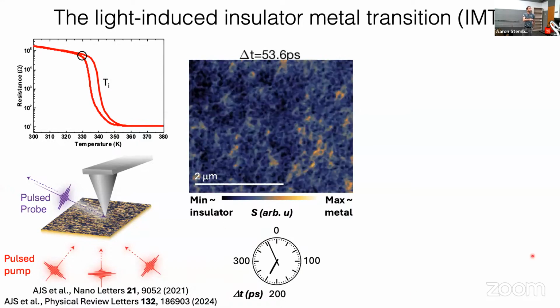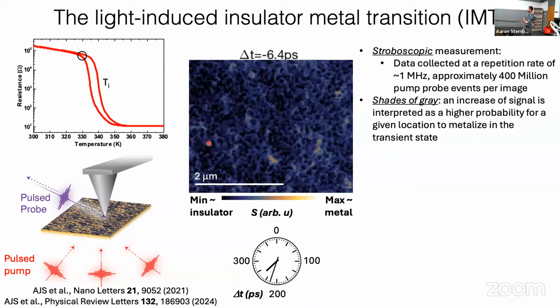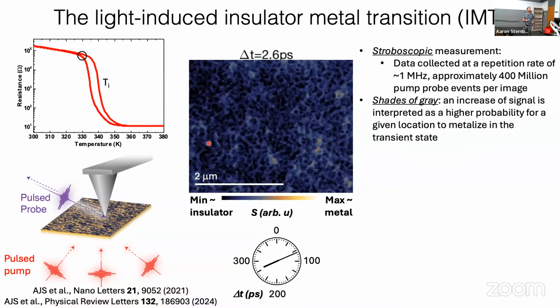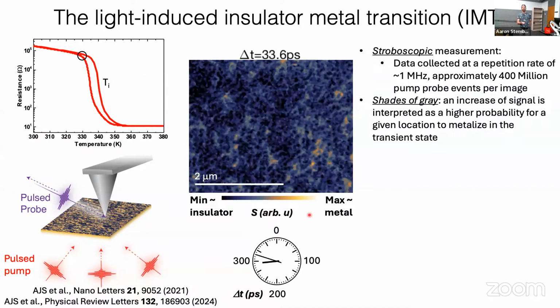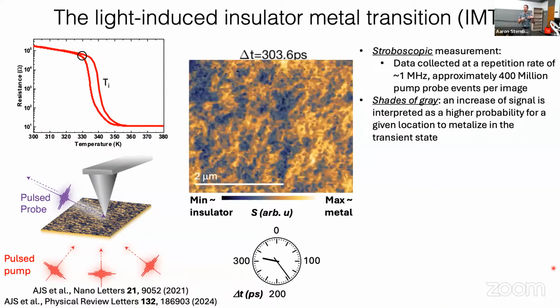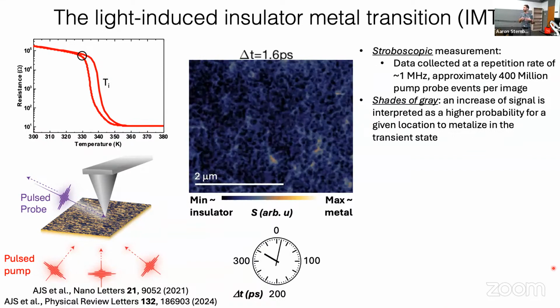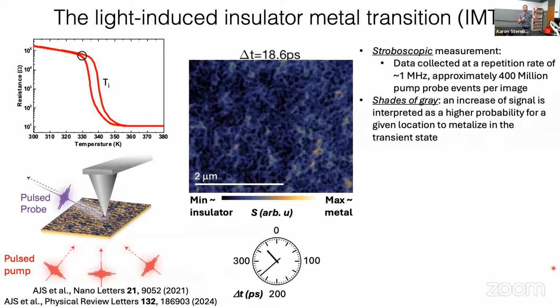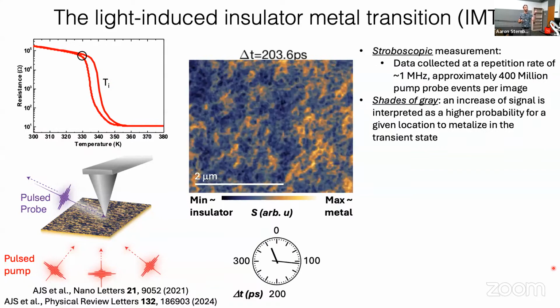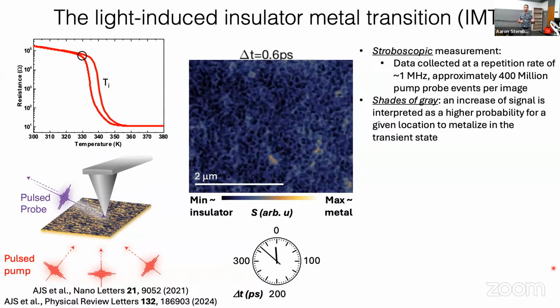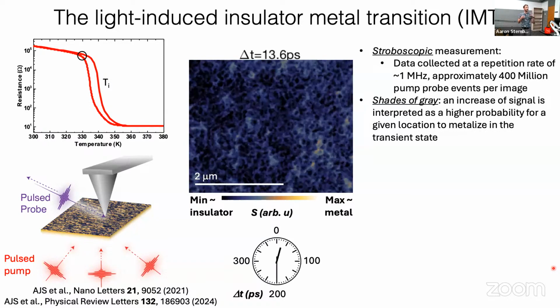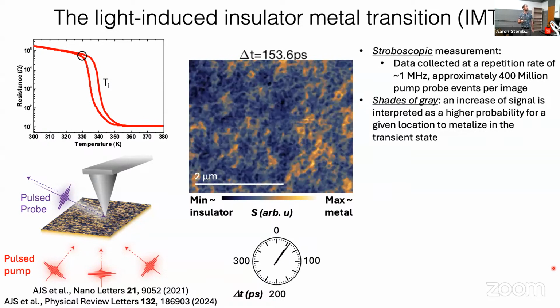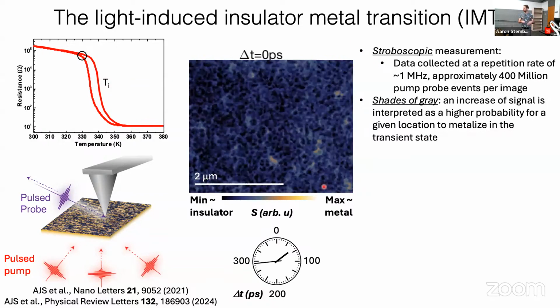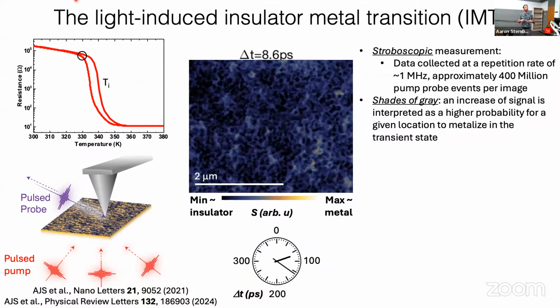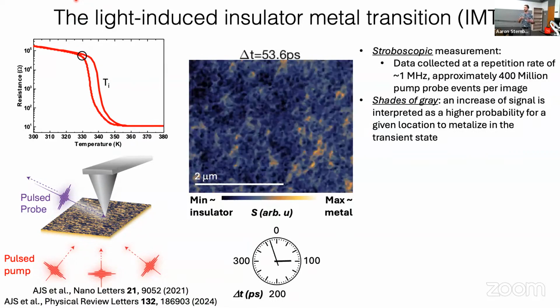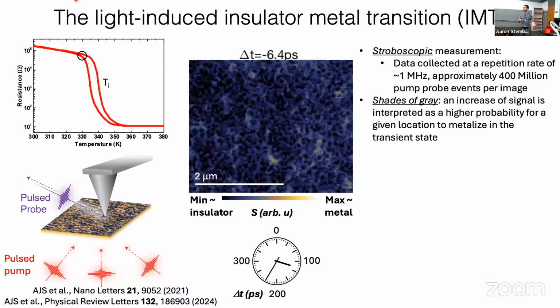So while this map gives you some impression that the transition is inhomogeneous, I want to highlight some of the subtleties. First, this is a stroboscopic measurement. So what we're doing is we're coming in with a train of pulses at a megahertz repetition rate. And this image is collected on a much, much longer time scale. So we spend a few milliseconds at every single pixel, and then we raster scan and collect data at 200 by 200 pixels to form an image at one time delay. And so this whole movie involves a sequence of pulses that is approximately 400 million different pump probe events.